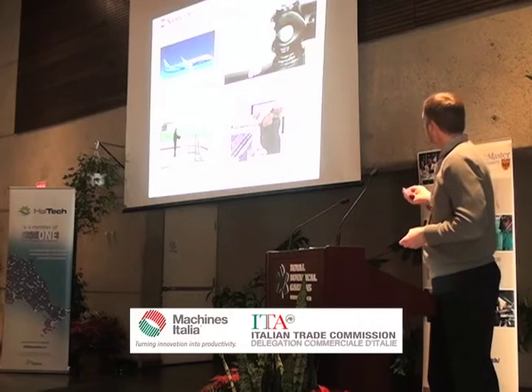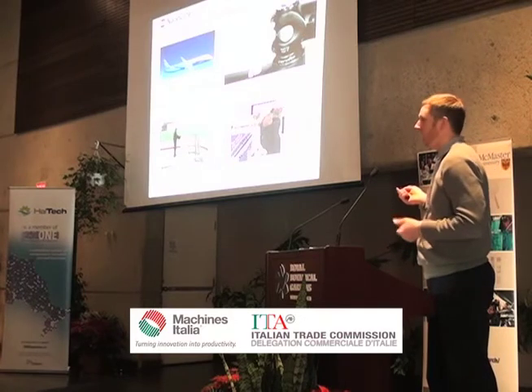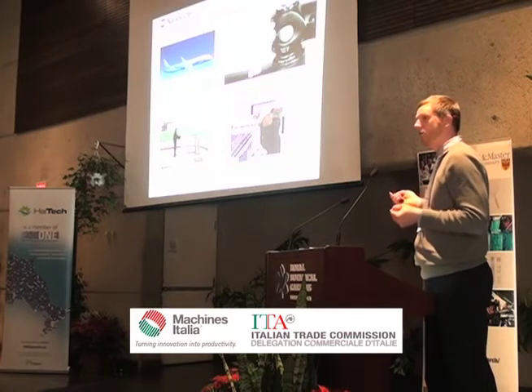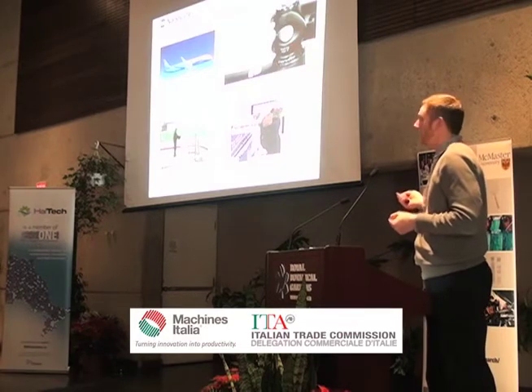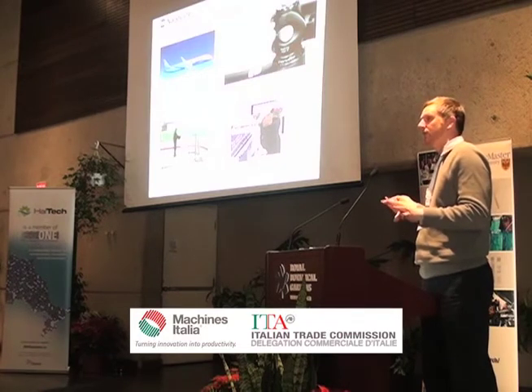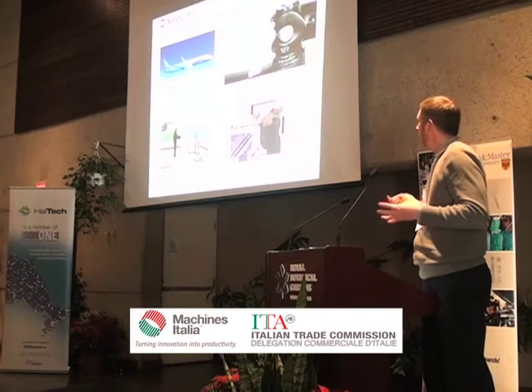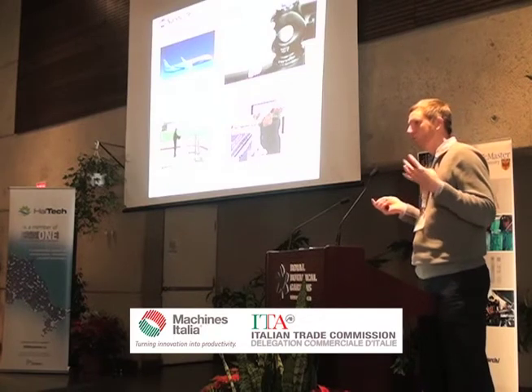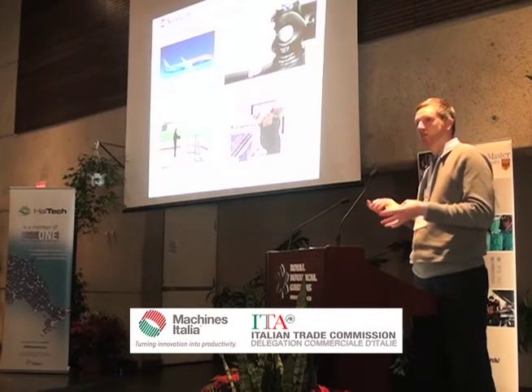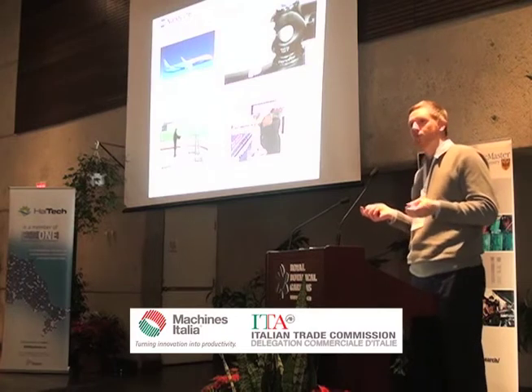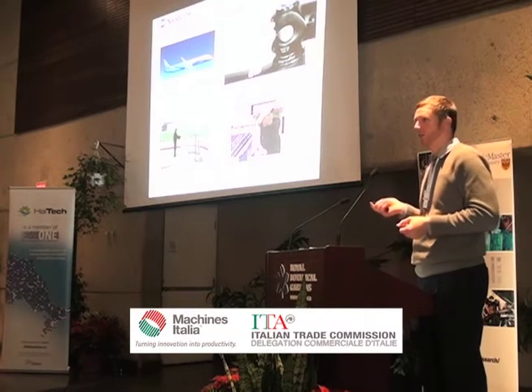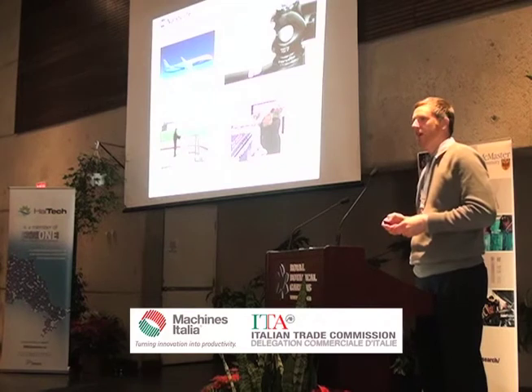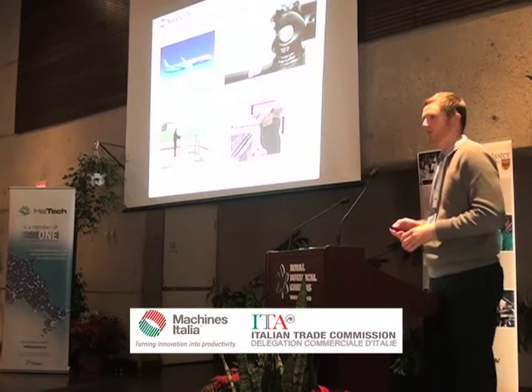Well, what we were able to do is add a strong, tough structural cladding to that composite part, and now when you undergo the impact event, the metal takes the brunt of that, and you're able to retain the properties of the composite so that it still has its performance. Afterwards, they were able to run that same test. It ran for 200,000 cycles, then they just shut off the test because, all right, that's good.